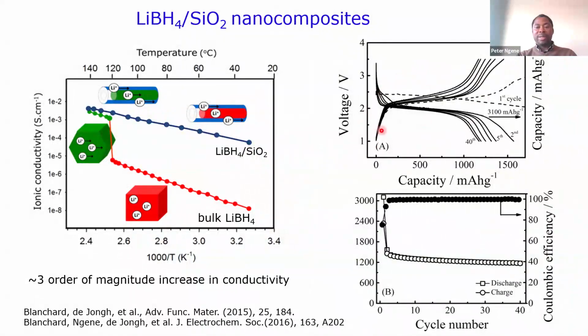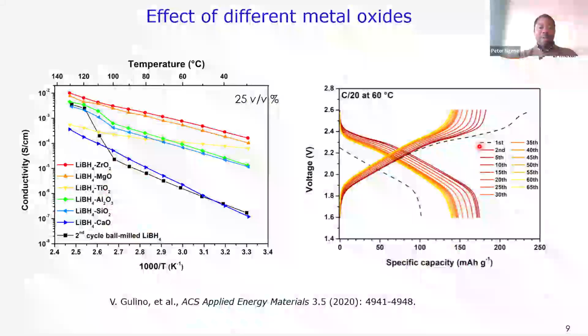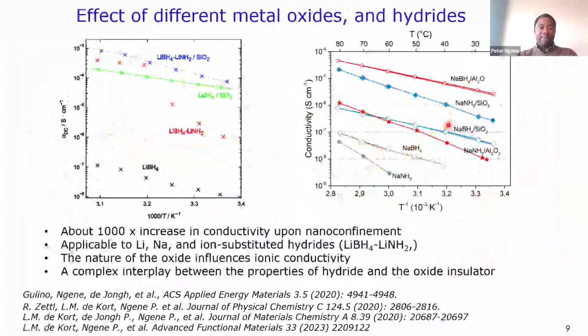And we demonstrated you can use that to make a battery. I think this is one of the first lithium sulfur batteries based on lithium borohydride. Here we have lithium, and then lithium sulfide as our cathode, and we can do this reversible reaction. So this is a lithium sulfur battery really based on this lithium borohydride. You can see we can cycle it, of course, up to 40 times, and now we have better results. But it's just a first proof of principle that this actually works. We have extended this research to many other types of oxide, and we're also using them to realize batteries that can work at room temperature.